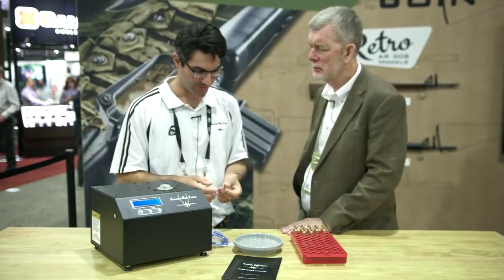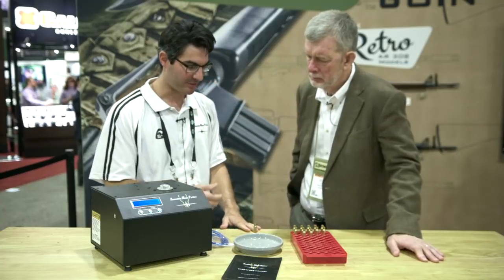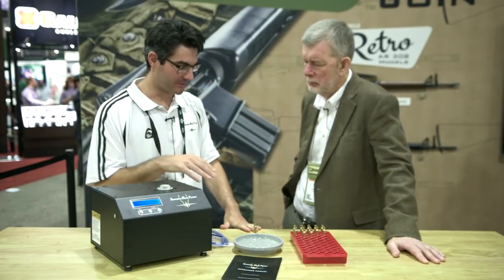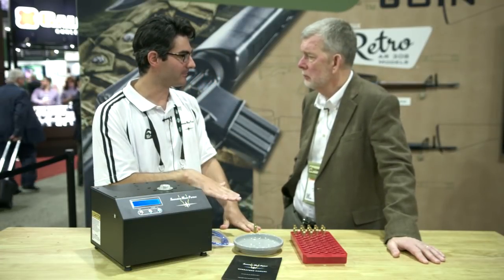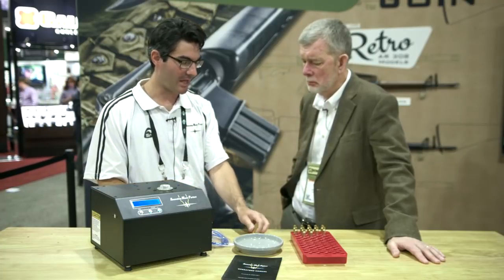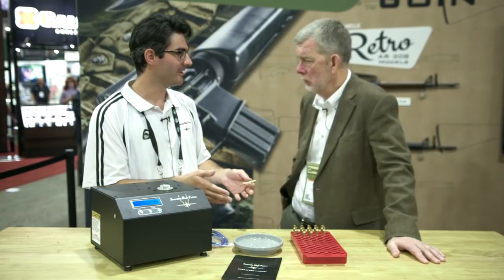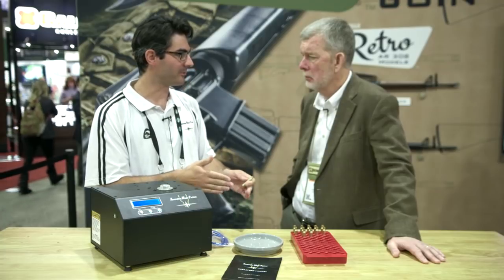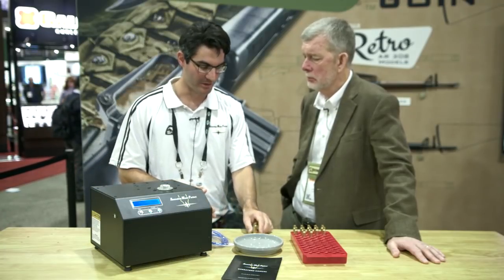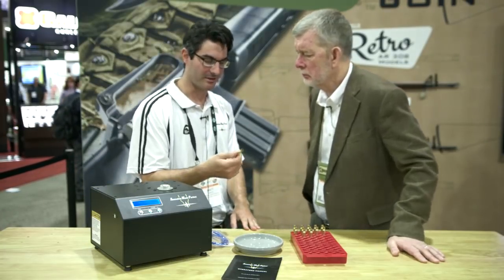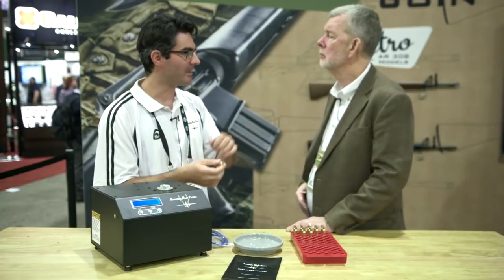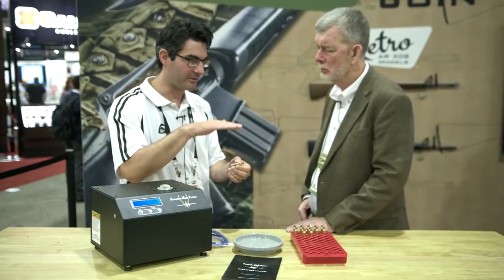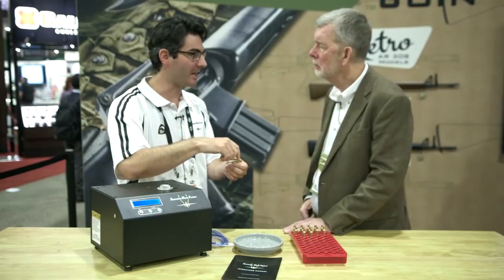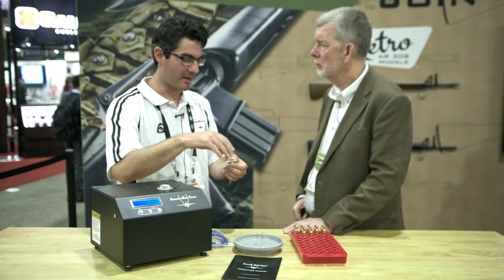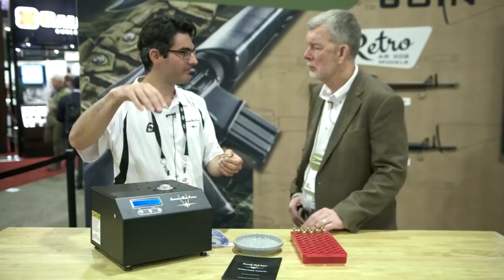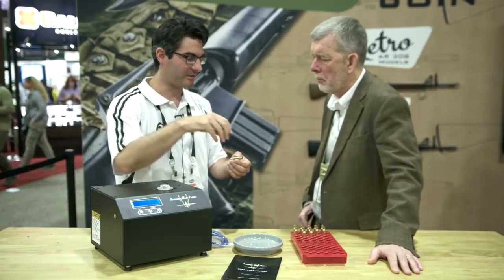So essentially we take the case, we measure it after we've annealed it to see what the hardness is doing. And what we know is factory brass out of the box is a certain hardness. And we've tried to replicate that as best as we can. Our research has shown, because we've loaded them up, fired them, loaded them up, fired them, and seen how the hardness for a given annealing, for a given hardness that we'd get after annealing, changes each shot. And what we're trying to do is get consistency.